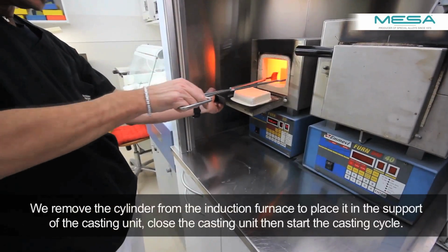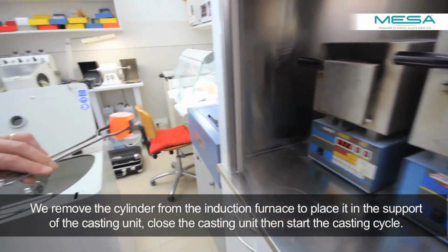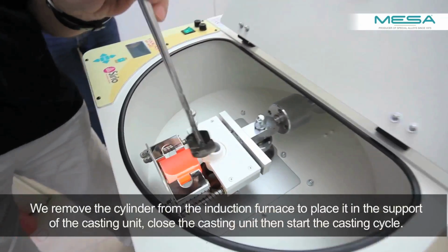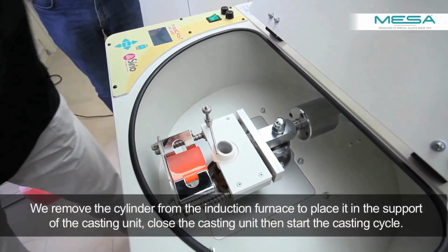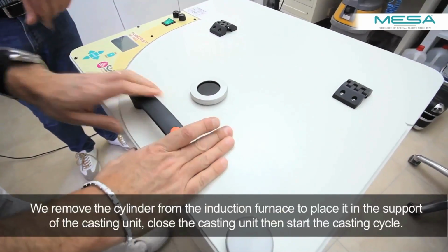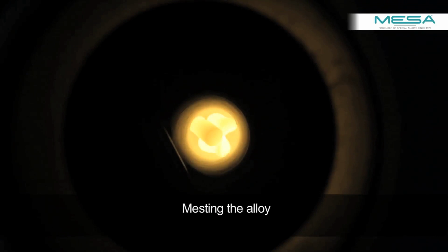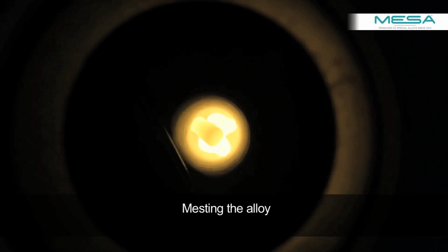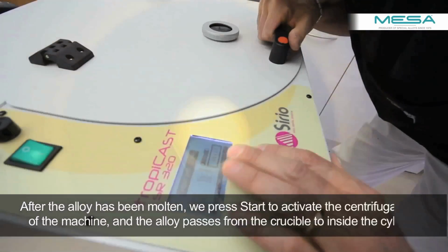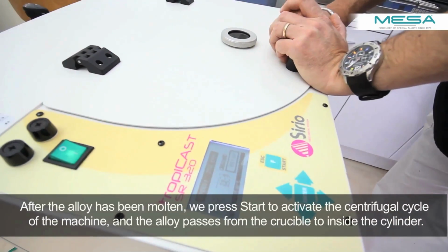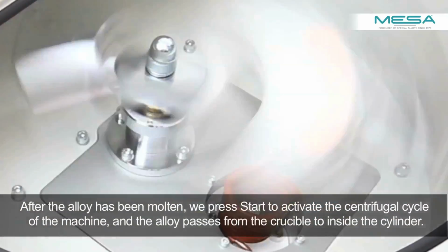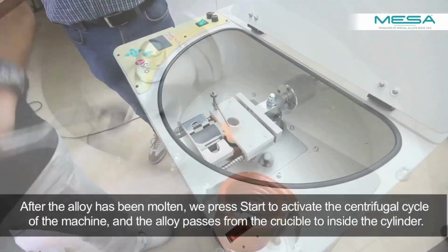We remove the cylinder from the induction furnace to place it in the support of the casting unit. Close the casting unit, then start the casting cycle. Melting the alloy. When the alloy is molten, we press Start to activate the centrifugal cycle of the machine, and the alloy passes from the crucible to inside the cylinder.